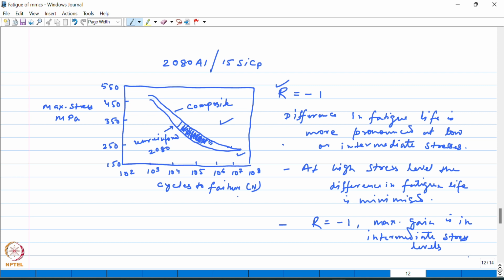Okay. So that's what you can see, if you go towards the lower stress or towards the right corner of this plot, you see that these two curves, these two plots kind of merge with each other, right? So there is hardly any difference in the fatigue life of these two materials. Lower stress or high cycle fatigue behavior of the composite and the unreinforced alloy is very similar.